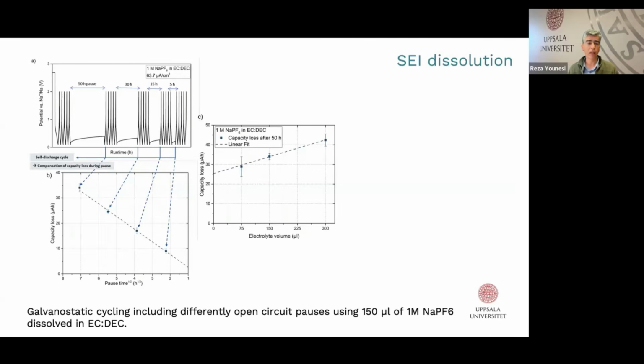What you see on top left, this pause was applied for different variations of time. By this, we could see on the bottom figure how much capacity is lost during the pause. We can see a linear relation between capacity loss and the square root of pause time, which indicates that this is a diffusion-based mechanism.